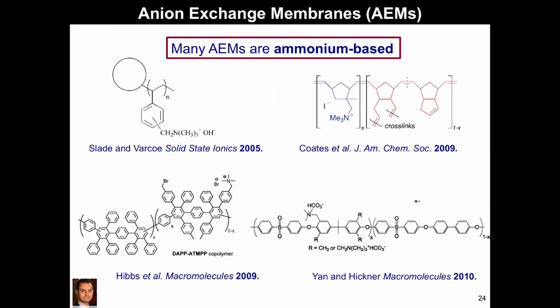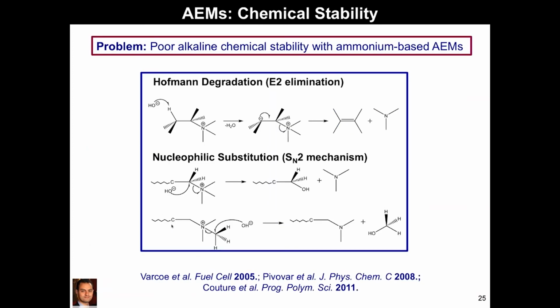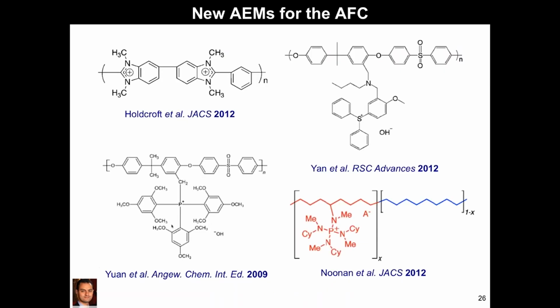And so here I'm just showing you on slide 24 some examples, some chemistries that have been introduced. And some of the things you may notice is that many of the chemistries are ammonium-based as the covalently attached cation. And what some investigators found early on is that these chemistries degrade pretty rapidly in an alkaline environment through E2 elimination or Hofmann degradation and nucleophilic substitution or the SN2 mechanism. So to combat that, a number of well-known groups have looked at some more exotic cations here. I'm just showing some examples and looked at the chemical stability and tried to improve that for this application.